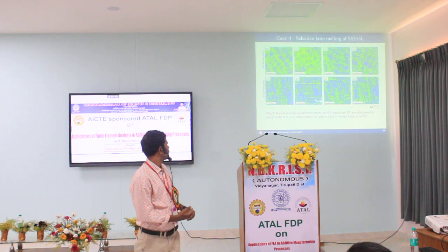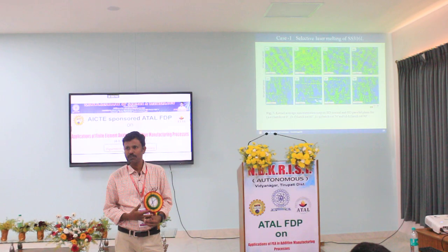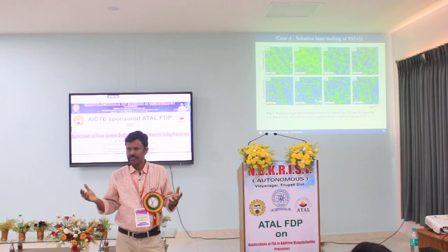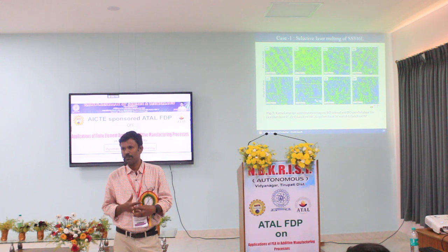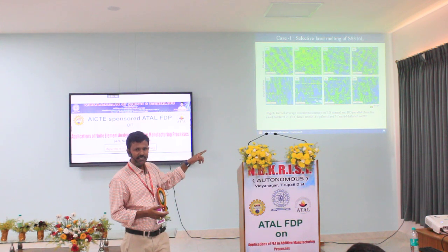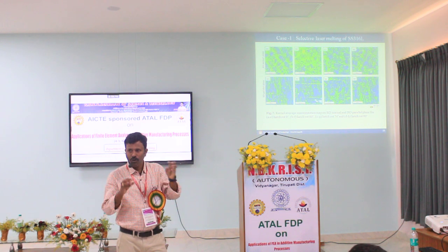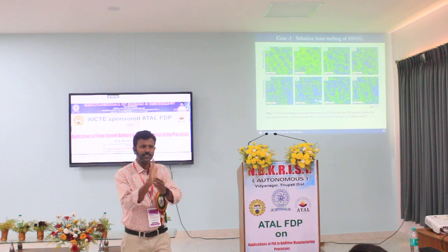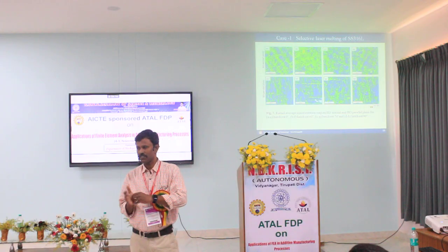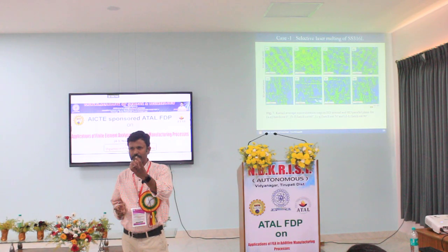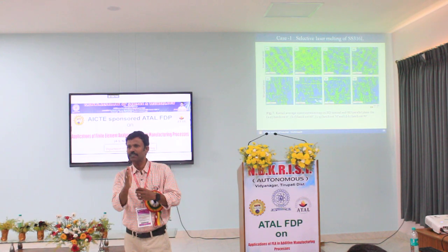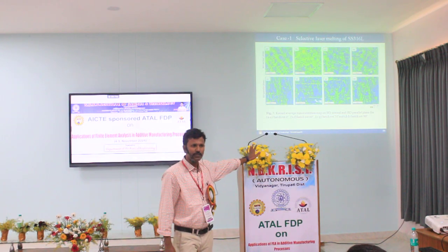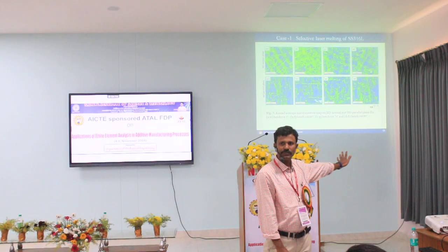This one is what we used to call the kernel average misorientation map. The color variation will give you strain variations. In fact, it is also called a micro strain map. A color to the adjacent color shows how much localized strain variation is there. So you can understand at the grain boundary, adjacent to the grain boundary, how much strain variation is there. If a second phase is there, at the interface and the first phase, what is the strain variation? All this information you can get comfortably from this KAM map.